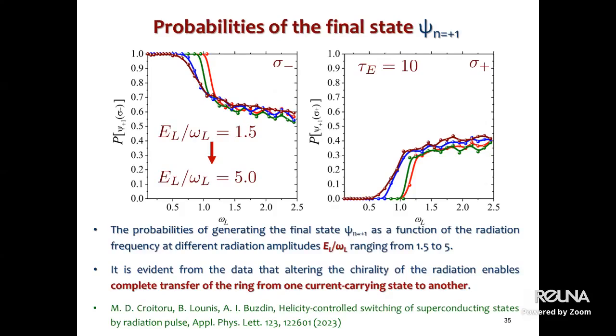One can clearly see that sigma minus radiation with intensity larger than 1.5 induces 100% switching at low frequency. Increasing omega to a maximum, and this maximum depends on intensity, leads to a drop of the switching probability. And then the probability for extremely large frequencies approaches 50%, which is useless for engineering application. We see this maximum threshold decreases as we increase the amplitude.